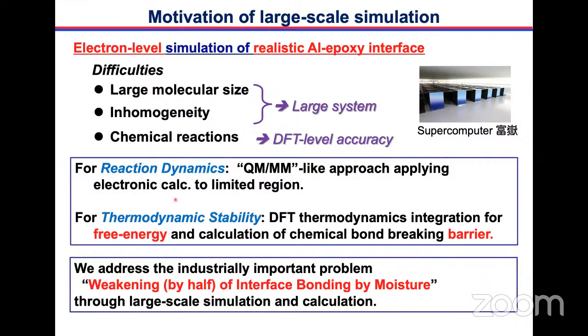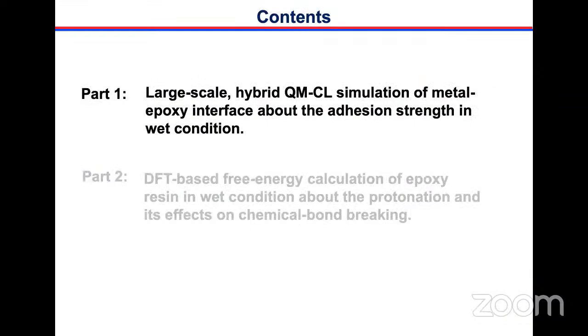Then we address it from two directions. One direction is that we use reaction dynamics by using the QM/MM hybrid method. In this method, we apply the electronic structure calculation only to limited regions. The other approach is the thermodynamic analysis, using DFT-based thermodynamic integration to get the free energy of each state and the chemical bond breaking barrier energies. We use these two methods to address the industrially important problem of the weakening of the interface bonding by moisture, through computer simulation and calculations. This is the first part, hybrid computer simulation.